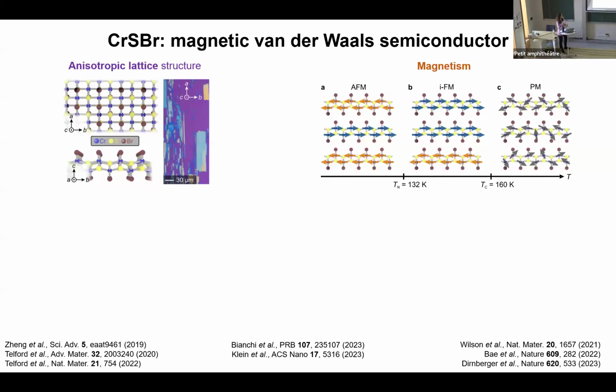Slightly above the Néel temperature, between the Néel temperature and the Curie temperature of 160 Kelvin, we end up having a mostly ferromagnetic spin arrangement, both in plane and out of plane. And above the Curie temperature, we have a paramagnetic state. I really draw your attention to these relatively high transition temperatures. So CrSBr can be easily studied with liquid nitrogen-based cryogenic infrastructures.